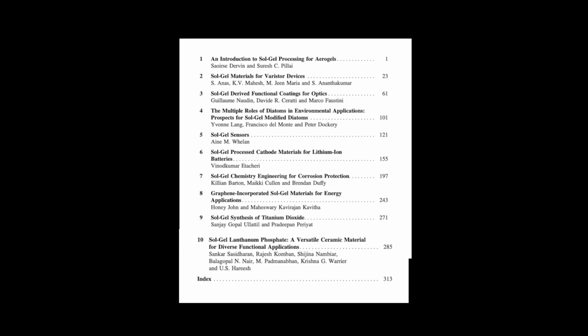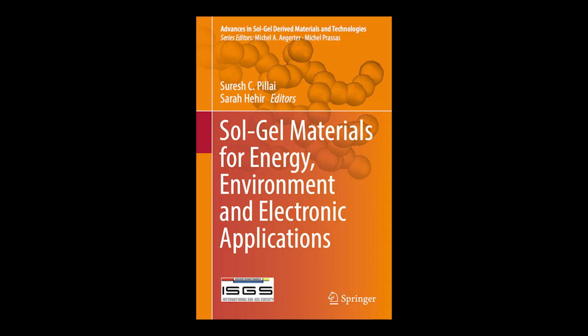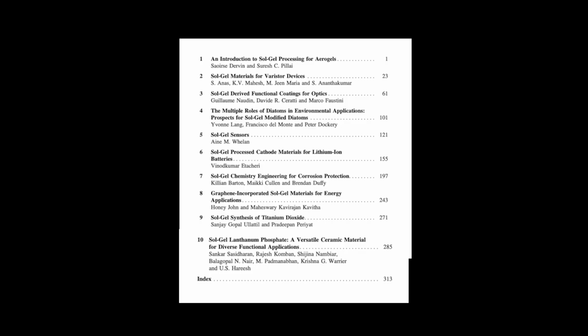And the processing benefits derived from using the sol-gel route are also huge for ceramics, right? It's not just about the final properties. Yeah. Oh, massive benefits. Because the sol-gel-derived LaPO4 powders consist of these very fine, nano-sized homogeneous particles, they enable what's called low-temperature sinterability. Sintering is the process of heating the powder compact to make it dense and strong. For LaPO4 made by sol-gel, full densification can be achieved at temperatures as low as 1300 degrees Celsius. For ceramics processing, that is revolutionary.